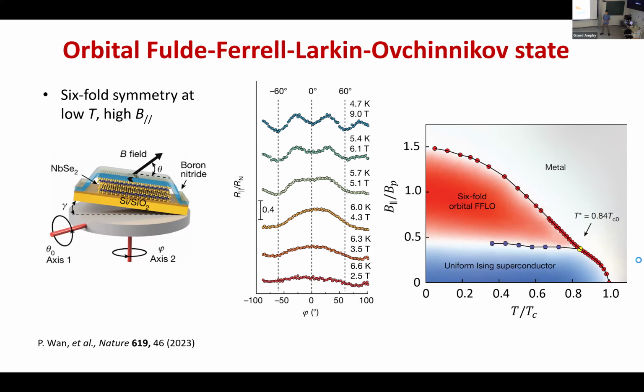So could you say again, there are red dots and then there are blue dots on the phase diagram? Oh yes, these red dots are just from resistance measurements. They determine where the transition was when you increase the field. A resistive transition, yes. And then these blue dots, they measure the critical current. They observe that along this point there is a bending of the critical current. When you apply the field, the critical current does not just drop down with the in-plane field; it drops, and then there's a kink, and then it drops further when you go to a higher field. So they mark out this kink as the phase transition line.